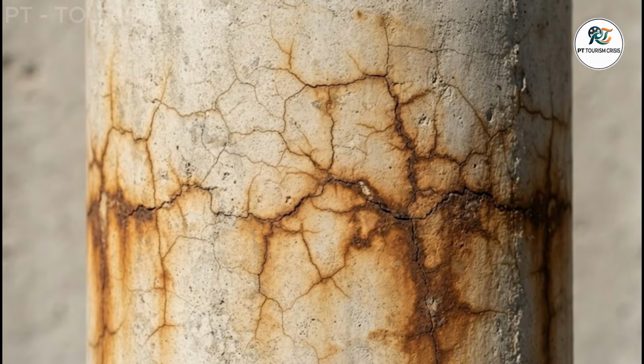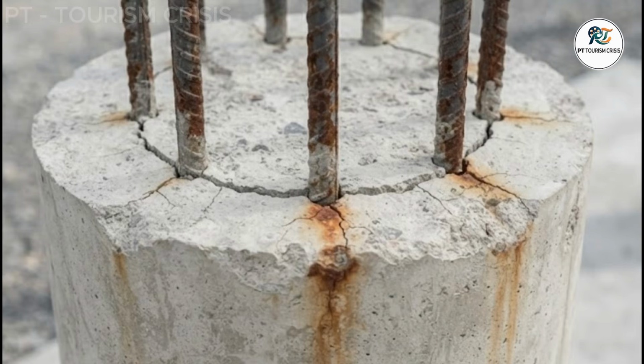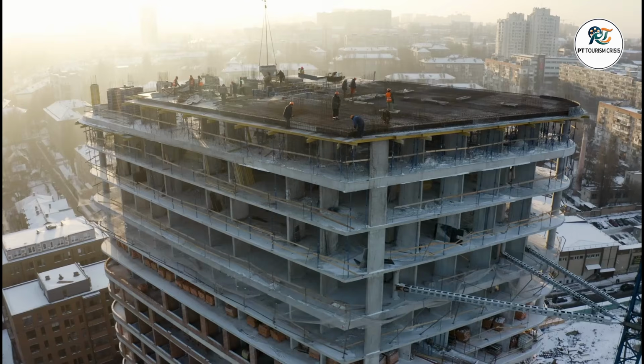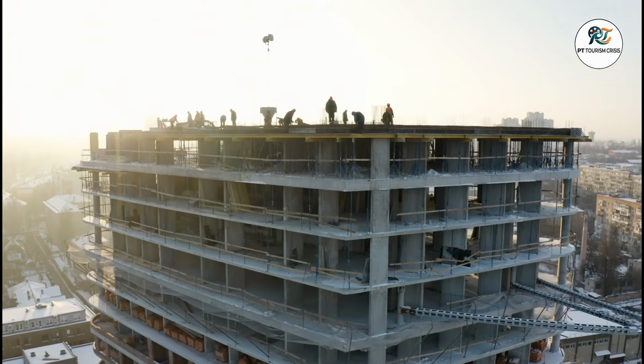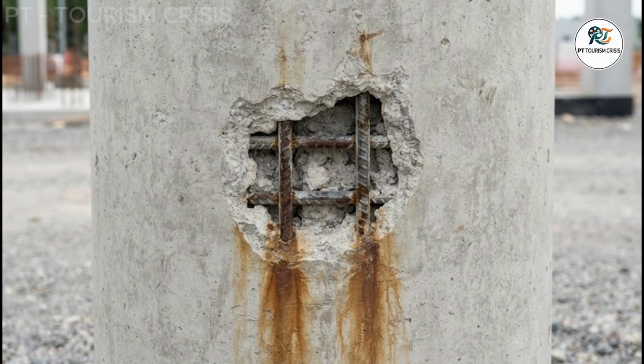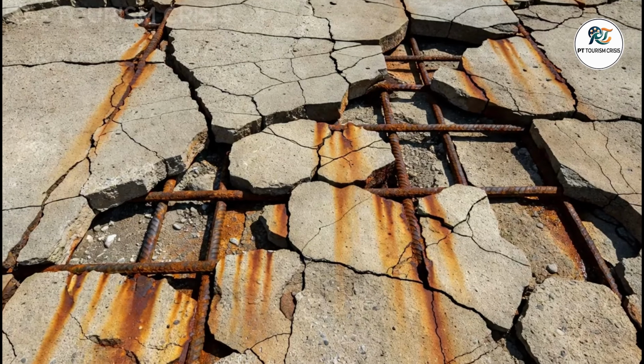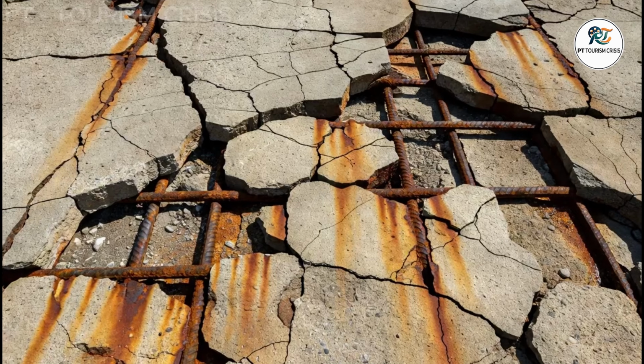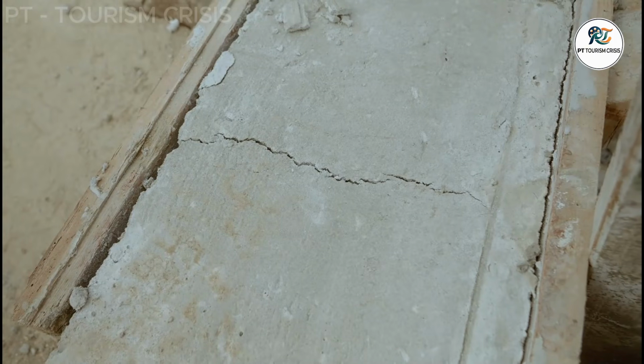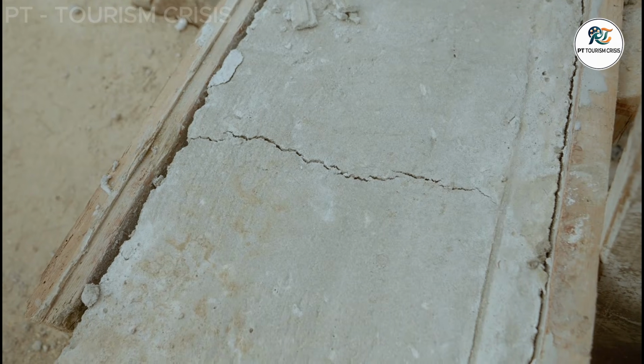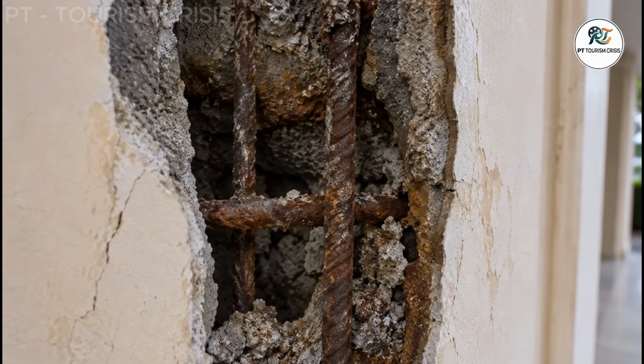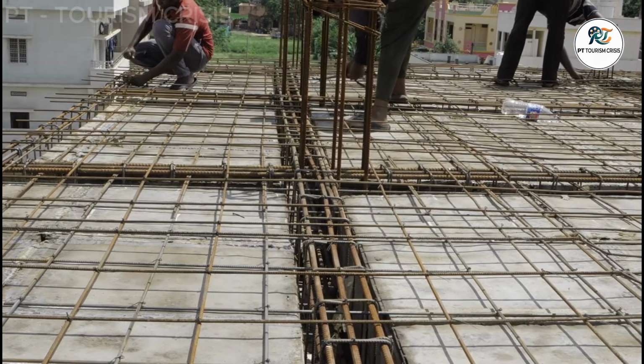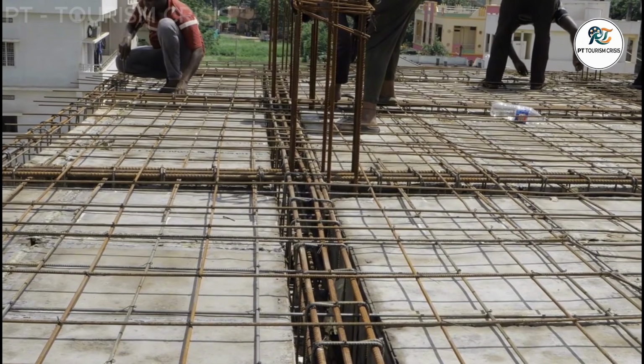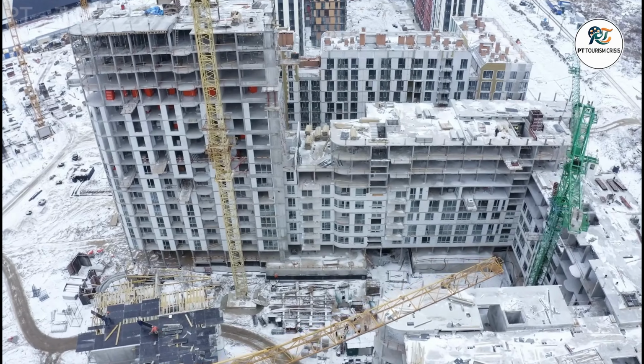This massive volumetric expansion creates immense localized tensile pressure, pushing outward against the surrounding concrete structure. Concrete is famously strong under compression, allowing it to hold up massive skyscrapers, but it is notoriously weak under tension. The material can only handle so much internal stress before it fractures, simply to relieve that immense pressure. An internal microcrack forms first, moving silently toward the exterior surface over a period of many months or even years. Eventually, that internal pressure reaches the surface, causing a visible crack or forcing entire chunks of heavy concrete to spall off completely. This specific chain of events means a severe physical failure has already happened by the time you can actually see the damage. But this raises an immediate structural engineering question.